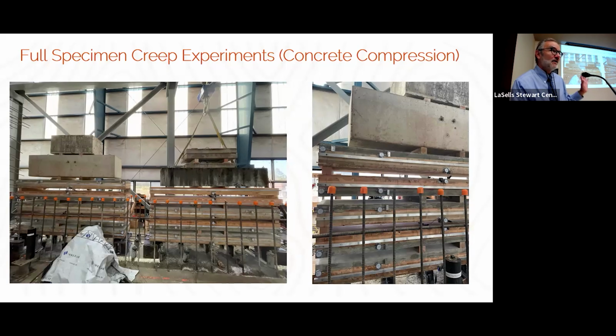Now this has got to stay here untouched for about a year or so, so it's got to be protected. We've got a cage of reinforcing steel to keep people from bumping into things. You can see how much weight you've got to stack up on top of those in order to get the fastener demand that we predict in them. This one has a little bit less load because that's targeting the lower value of shear force. And here you can see again manual measurements of the vertical deformation, as well as the slip deformation that's occurring between the concrete and the CLT. And now we wait, except you've got to go out every day and take pictures with your iPhone.